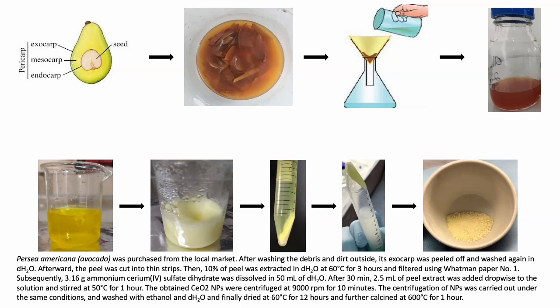paper. Subsequently, 3.16 grams of ammonium cerium sulfate dihydrate was dissolved in 50 milliliters of distilled water. After 30 minutes, 2.5 milliliters of peel extract was added dropwise to the solution and stirred at 50 degrees for 1 hour. The obtained nanoparticles were centrifuged at 9000 RPM for 10 minutes. The centrifugation of nanoparticles was carried out under the same conditions and washed with ethanol and distilled water, and finally dried at 60 degrees Celsius for 12 hours and further calcinated at 600 degrees for 1 hour.